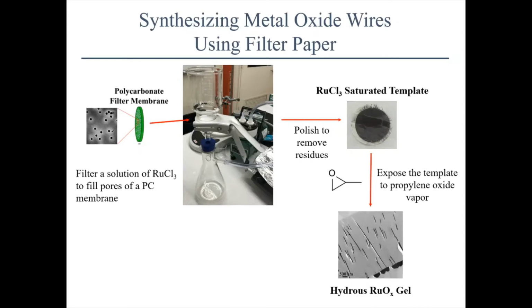So you mix those two chemicals up in a beaker, and then what you vacuum pull through the template is the ruthenium oxide gel. It's already been gelled, and you're just loading the template with the gel. When we tried that using the normal literature protocol, we found that it did not lead to good results. It mostly clumped up on the surface of the template, and it didn't really give us a good nanowire result. We didn't get a good morphology from that.